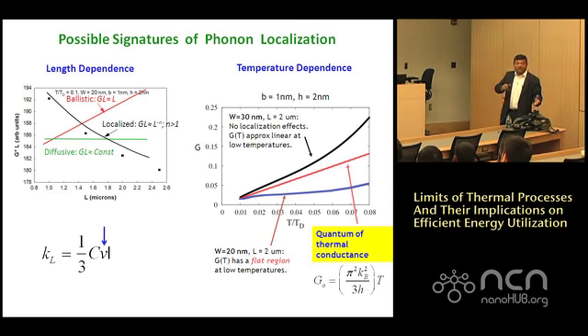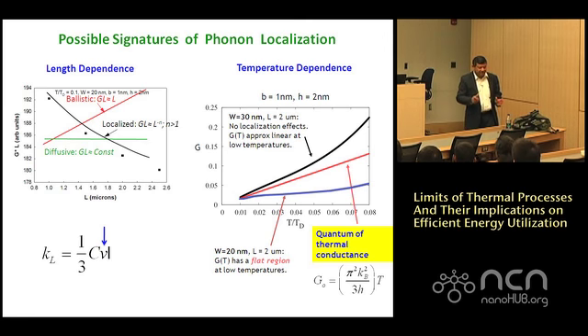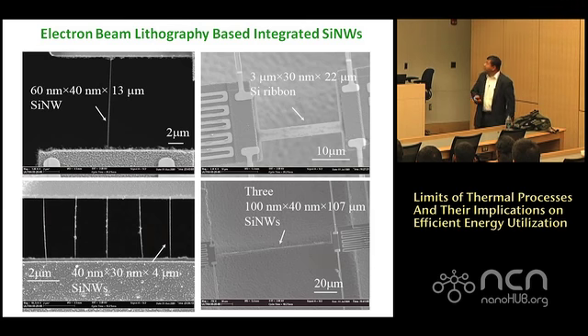So instead of making these nanowires separately, we said that this issue about contact resistance is a big deal. We need to control the size, dimension, and everything, and putting wires on a device is not the way to go. So we changed our whole experimental system. We are now making electron beam lithography wires integrated in the silicon; the nanowires are integrated together and made of the same material as the heater. This is using silicon-on-insulator wafers, making the pattern. Everything is integrated. When you do e-beam lithography and photolithography, you can control the length, the dimension, everything. And since it is monolithic, there is no contact resistance. That's the way to go if you really want to get into the science and understand this in the right way.